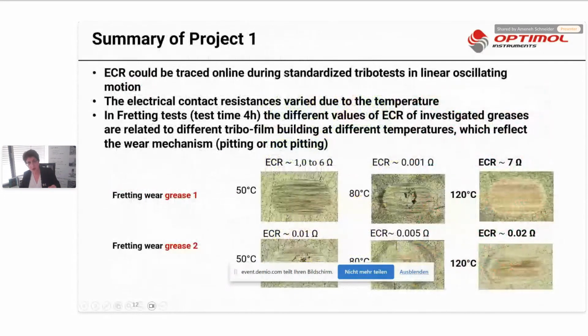When I summarize the result or the insight that might be interesting for you from this project, it is that this electrical contact resistance sensor really gives you valuable additional information. It varies due to the temperature. And because we have a long test time, which is 4 hours, we believe that it is also related to the different tribofilm building.